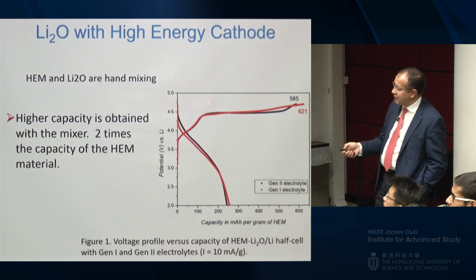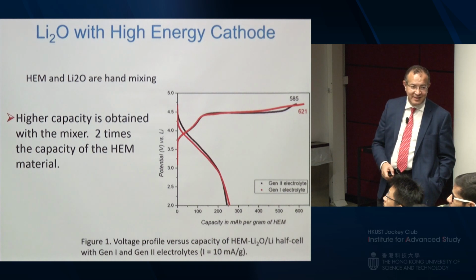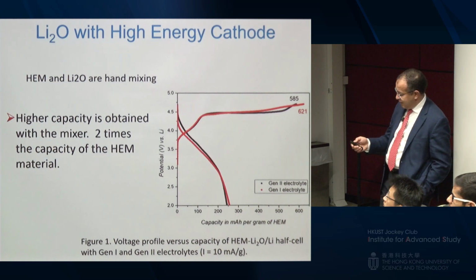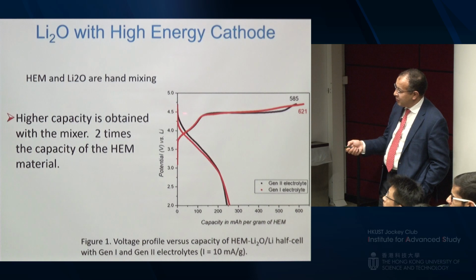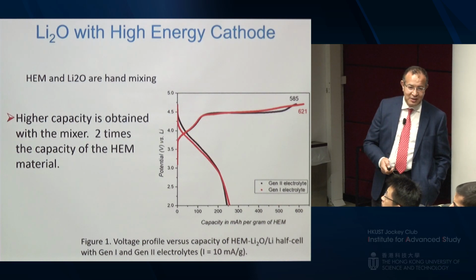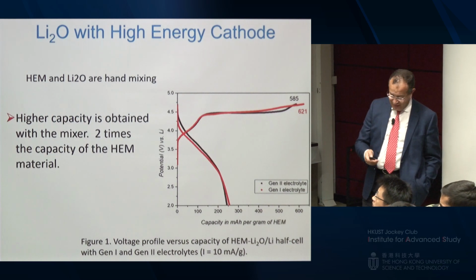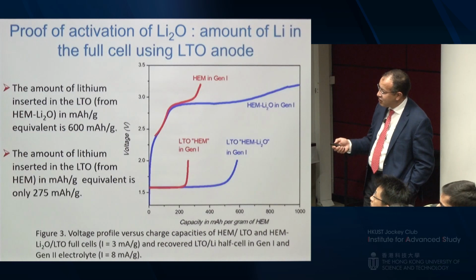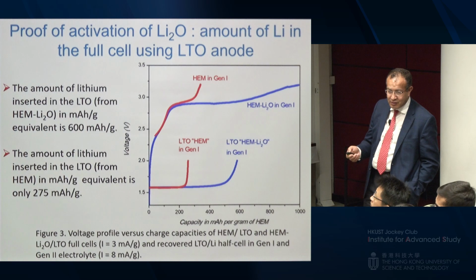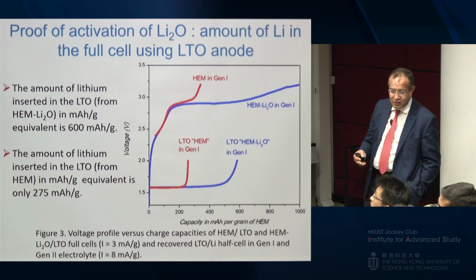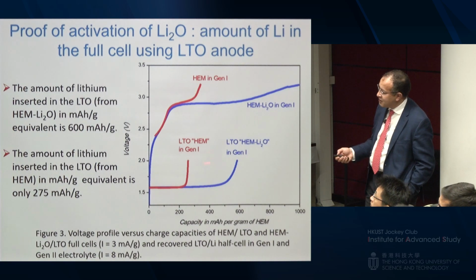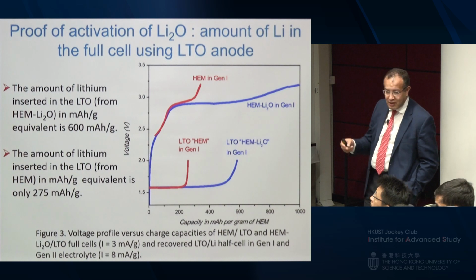Just 1%, you get almost 300 milliampere per gram. Obviously, you may think we are operating at high voltage, and therefore this could be just a decomposition of the electrolyte. So to prove that, we actually took it to LTO. LTO has 100% efficiency. So you can design your cell to get you the capacity you need.